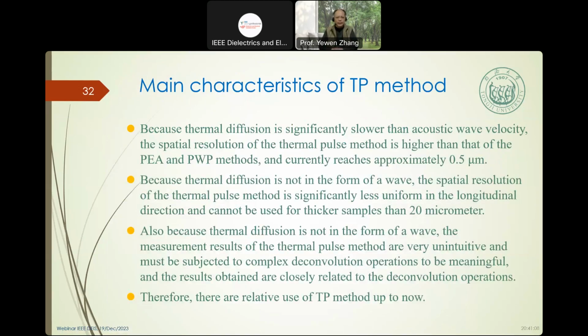So the main characteristic of the TP method is that thermal diffusion is slower than the acoustic wave velocity. So the spatial resolution of the thermal pulse method is higher than that of the PEA and the PWP, and can currently reach about 0.5 micrometer. Because thermal diffusion is not in the form of a wave, the spatial resolution of the thermal pulse is less uniform in the depth direction, and it cannot be used for thick samples over 20 micrometers.